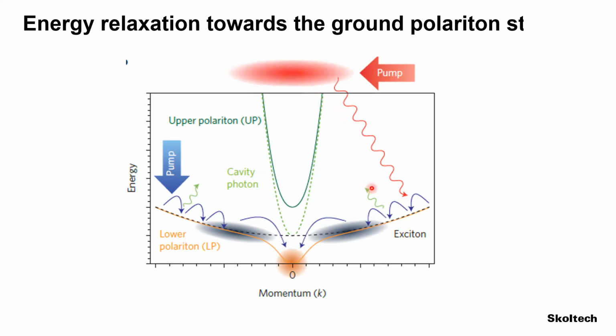And once these excitons relax from very high in-plane momenta outside the light cone, they relax in energy, and eventually they form polaritons. And what you want is to create a high enough density of polaritons so that you reach occupancy of 1 at the ground polariton state, and then through stimulated relaxation, all polaritons will go and form a macroscopic coherent state, the Bose Einstein condensate of polaritons at the ground state.